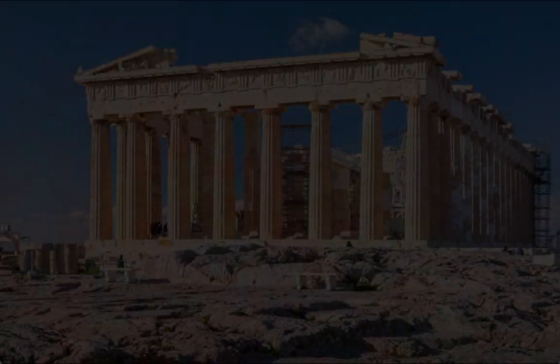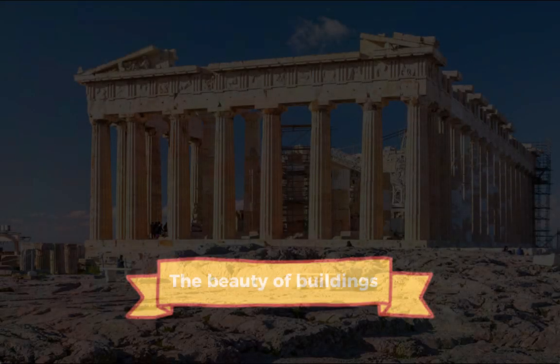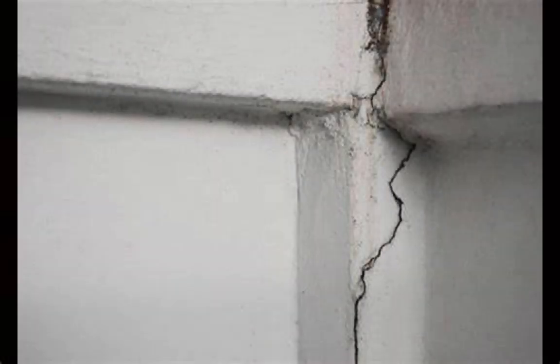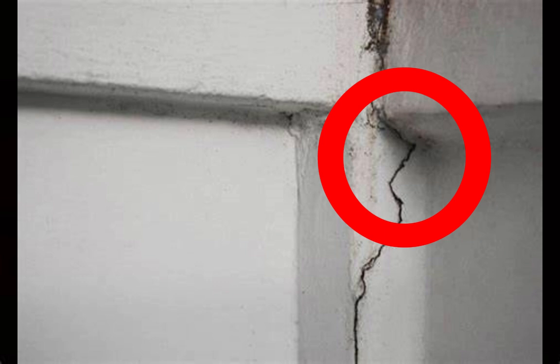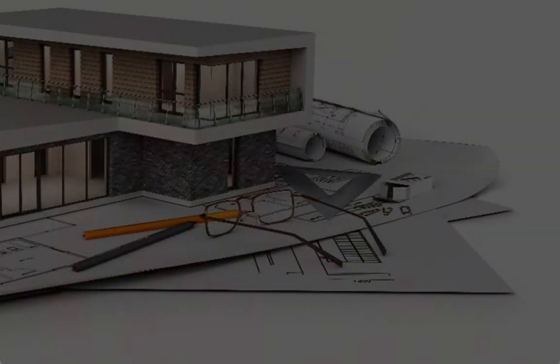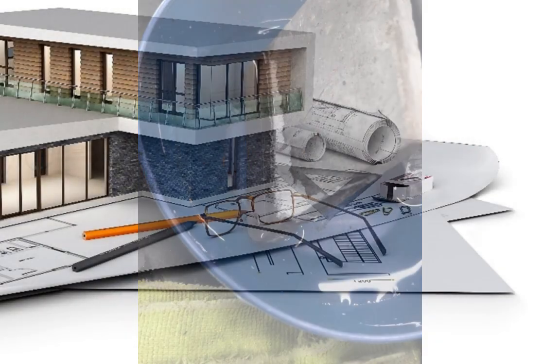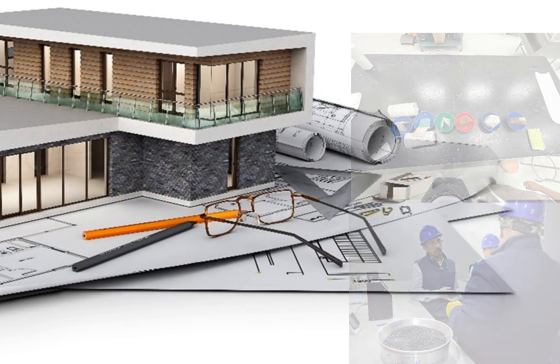The implications for architecture are significant. Efflorescence not only affects aesthetics, but can also indicate structural issues, as expanding salt crystals may cause microcracks and eventual failure. In summary, our findings highlight the mechanisms of efflorescence in ceramics, stressing the importance of material choice and environmental factors in design.